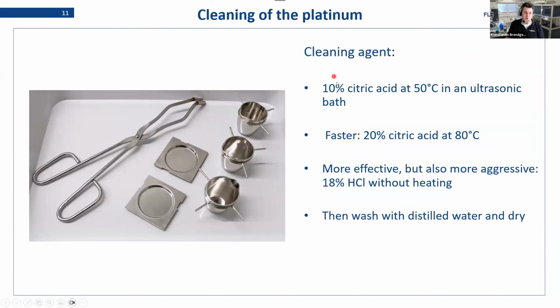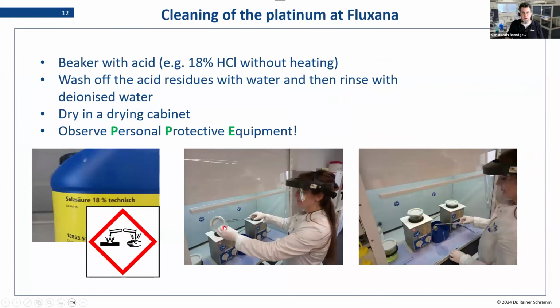So what acid do we use? There are multiple options here. Citric acid is one that people prefer because it's easily available and not very hazardous. You can heat it to 50 or 80 degrees. What does FLUXANA use? We are actually using HCl here because, well, it works for us. It goes very fast. And the idea is you leave it in the basin, you give it the ultrasonic treatment for a few minutes, and then you take it out like my colleague is doing here.